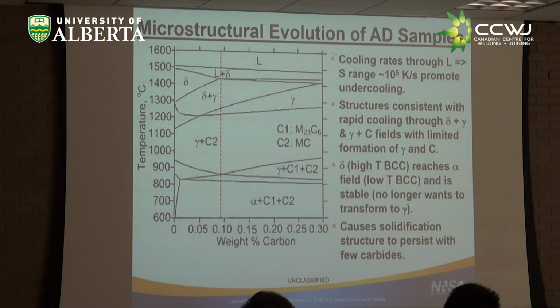So back to the phase diagram, and here's the whole punchline of the whole presentation. Cooling rates, as I said, we think are on the order of about 10^5 K per second, if you believe all this. Under equilibrium conditions, the phase diagram tells us we should undergo this sequence of phase transformations, which we don't see microstructures consistent with. We see something different.